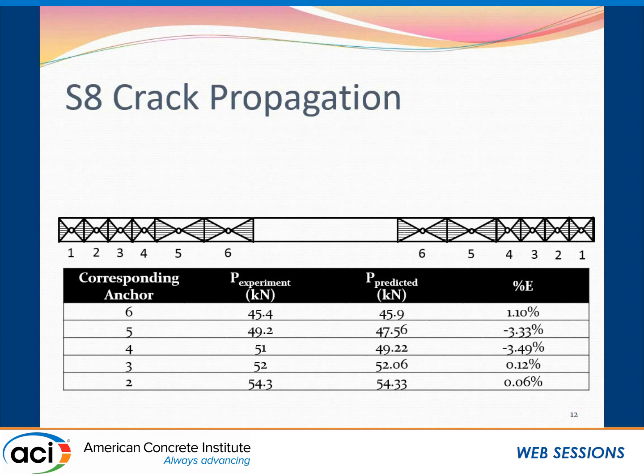So I believe in the paper it was mentioned that it was done visually. They recorded the loads at which the crack was visually observed to be at each location. Then in our analysis, we placed the anchor at that location, assumed that the crack was there, and obtained the load. Yeah, the cracks were measured visually, because my students did the work. There may well be some variation, but what you've done there is really good work. You've predicted the response really well. Thank you. Great work.